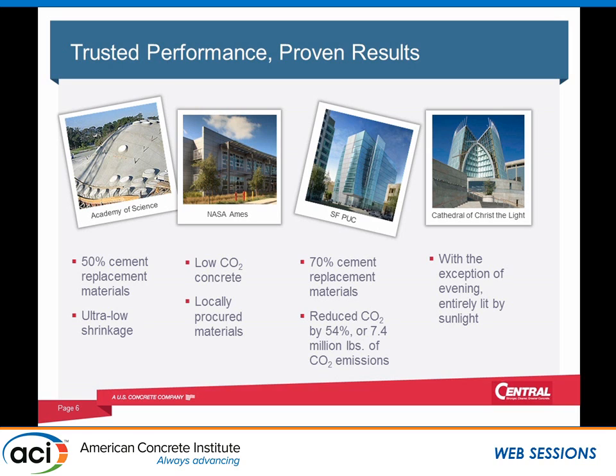What we found out, what Karthik was talking about earlier, some of the benefits of doing different types of testing at different ages. So this was actually the specification when we met with Tipping Mar when they were first doing some of the preliminary designs, was to move the specification from 28-day strengths all the way up to 90-day strengths. And we did a lot of work on the maturity testing to ensure that they get the strength that they want when they need it.